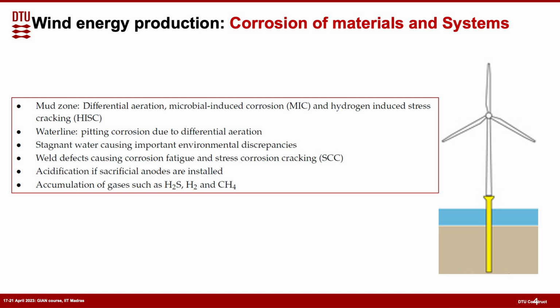Acidification: if sacrificial anodes are installed, that means metal dissolution is taking place in the sacrificial anodes, and that is creating hydrolysis, and that way it produces acid conditions. That acid condition in turn affects the corrosion of this material. Yesterday we were talking about the other side, right? We were talking about the protection of the aluminium with the magnesium, and we were saying that if the magnesium is lowering the potential of the aluminum so much, then you can have more cathodic reaction on the aluminium, and that way you produce hydroxyl ions.